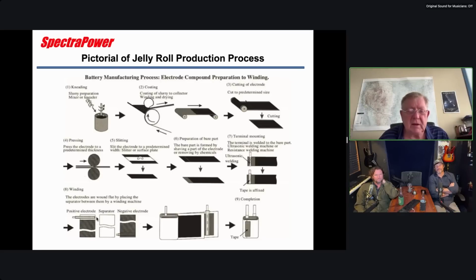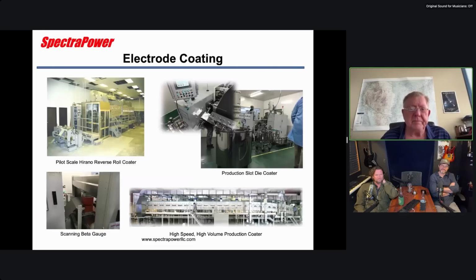And then you take the positive, negative, and separator, and you wind it up into the jelly roll. Here's a flat one, and then you have 2 tabs sticking out of it. Wow. You put it in a can and weld the tabs and seal the lid, usually with a laser welder, after you filled it with electrolyte, and then you're ready to charge it.